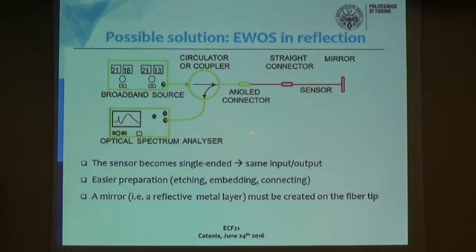So what we have conceived is a new kind of sensor, which is based on reflection. We found a way to easily produce a mirror at one of the sensor tips. So the sensor can now work in reflection. You have the source, which emits light, then a part of this light is back reflected, and there is this component, a circulator, that separates the forward from the back reflected light, and it goes again to the detector, the optical spectrum analyzer. So in this case you only have one connection, and the problem of fragility is somehow solved.